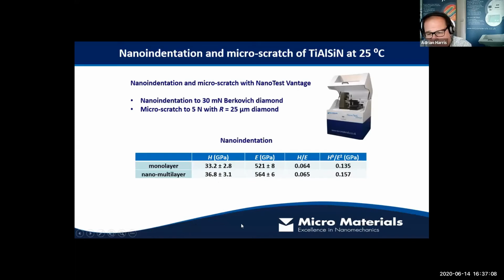So our nano indentation results are as follows. Similar hardness, there's 3 gigapascals difference there. The multi-layer is slightly stiffer than the monolayer sample. We can get some useful predictors out of nano indentation data, which we could use to try to predict how a coating might behave tribologically or in fatigue.